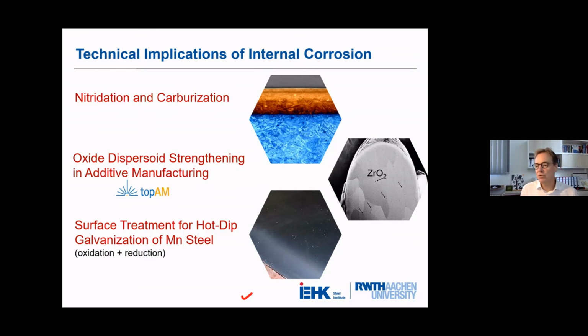And therefore, what we are doing is an oxidation treatment. Then we get an external iron oxide scale and internal manganese oxides, and then afterwards a reduction of the wüstite, and then we have a nice metallic surface that can be hot dip coated.